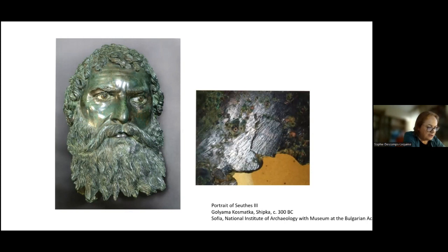The bronze alloy tarnished very quickly, an evolution that could happen only a few years after the manufacturing of the statue. This is why there were attempts to delay the onset of corrosion by coating bronze statues with bituminous substances or pine resin diluted in olive oil, as I said previously. And the head of Seuthes III probably remained in the open air for only a short time before being buried a few meters from the front of the Odrysian ruler's cenotaph.